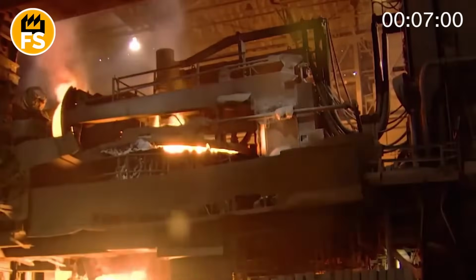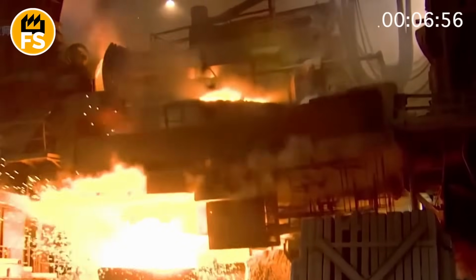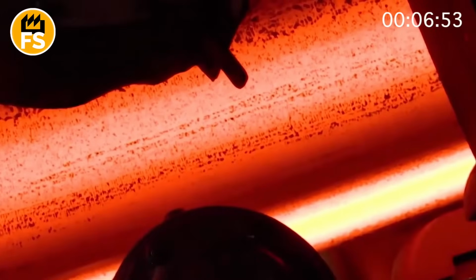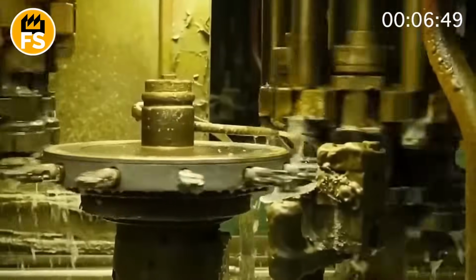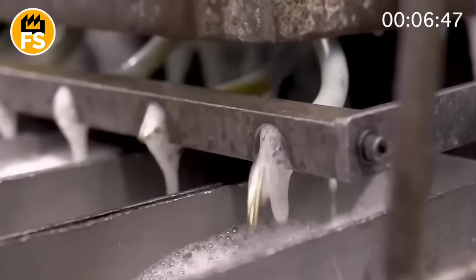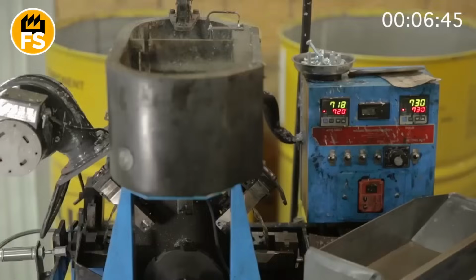Each casing is annealed after drawing. This involves heating it to 1,000 degrees Fahrenheit to relieve internal stress in the metal. Otherwise, the casing could crack during firing. Then, it's cooled in water and cleaned in an acid solution to remove scale and lubricant.